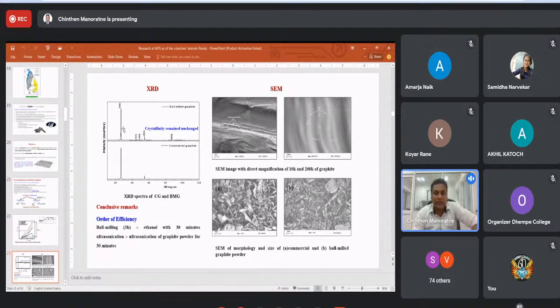Their crystallinity hasn't changed. And these SEM images show the layer structure of graphite at lower and higher magnification. The SEM images below show the commercial graphite has no special shapes. They are irregular shapes, needle, some are flake-like. But when you ball mill, their structure is damaged, and the particles tend to be more spherical.